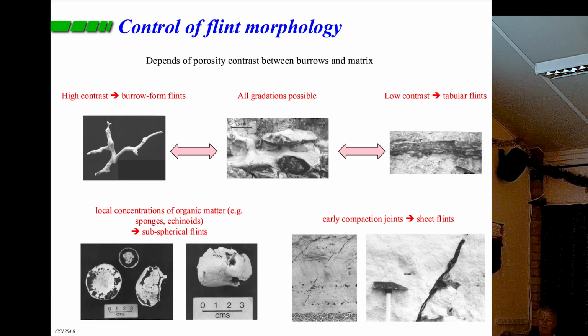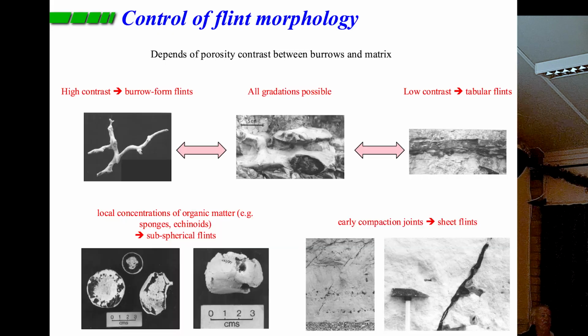If we've got hardly any burrows, just a flat sediment, then sure enough we get a tabular flint, solid flint right across. And we find all intermediates in here. For example, this sample here is part of one of these intermediate samples where we've had mixing within the burrow, but the flint has overgrown the burrow that's in there. And then just to complicate things, if we have isolated fossils that have got organic matter in them, we get the same thing. So we find fossil sponges or fossil echinoids which are silicified.